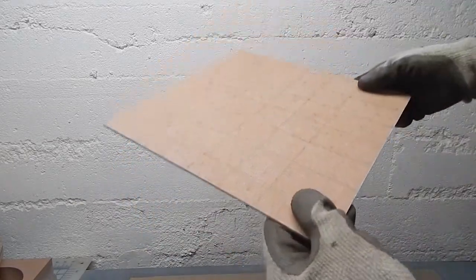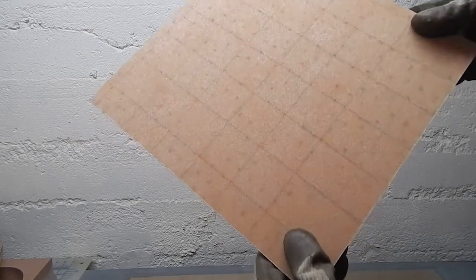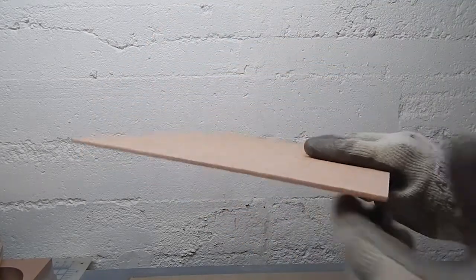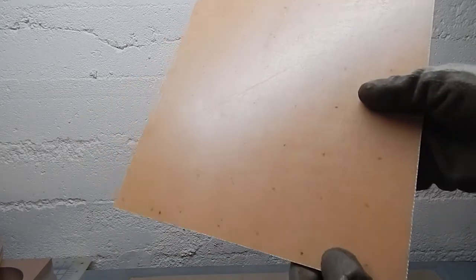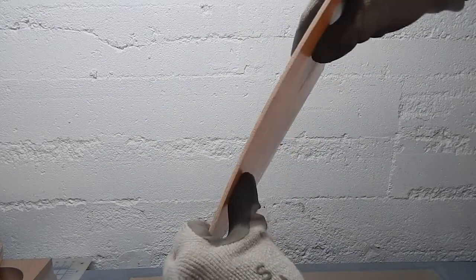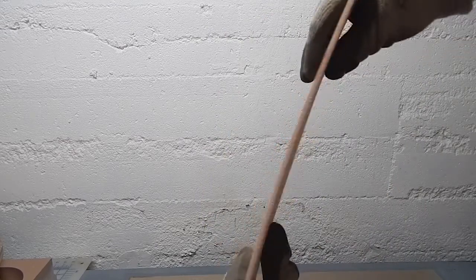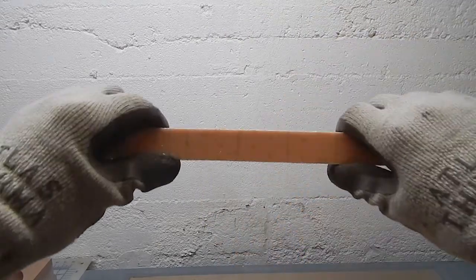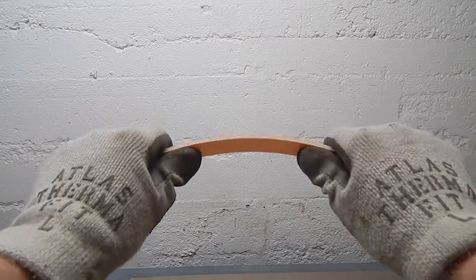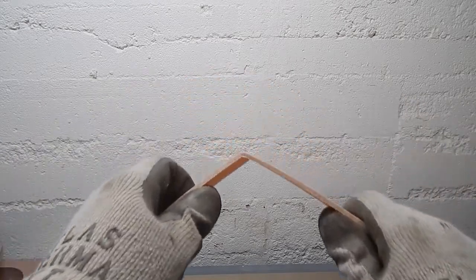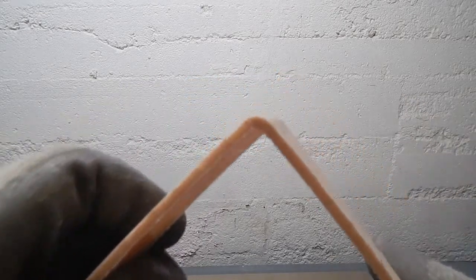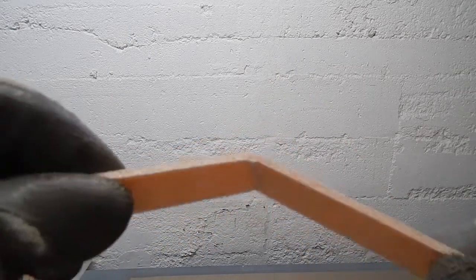Came out pretty nicely. There's definitely pinholes in the bottom skin. There's not much glass there, and not much resin. But it feels pretty stiff. It's definitely light. It's certainly a stiff enough panel to serve a lot of purposes that are not structural. But it definitely breaks. See, it failed on the compression side. Skin just cracked.